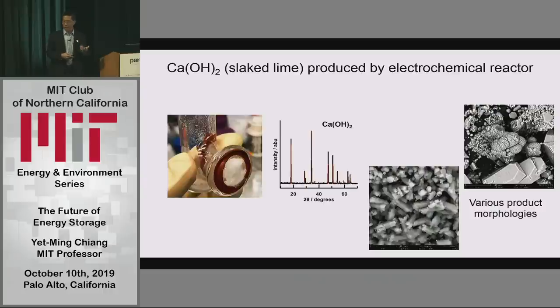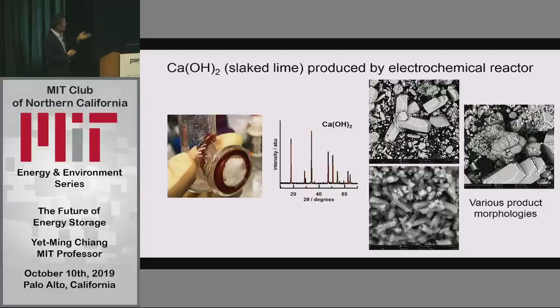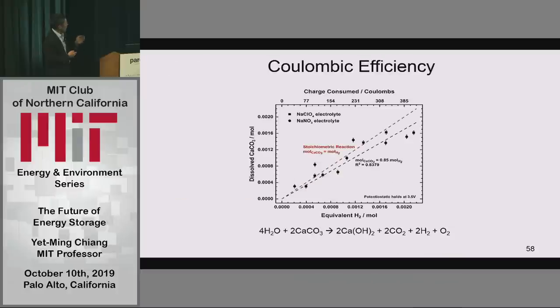is a precursor to cement. So instead of using calcium carbonate, we now use the calcium hydroxide because when that decomposes, it only releases water. Okay. And so we produce calcium hydroxide here, and it comes in all these different morphologies. And we can do so with, it turns out, very high efficiency, in terms of every electron that we put into the electrolyzer produces a certain amount of converted calcium carbonate. Okay. And so this is what we call the Coulombic efficiency of the device.